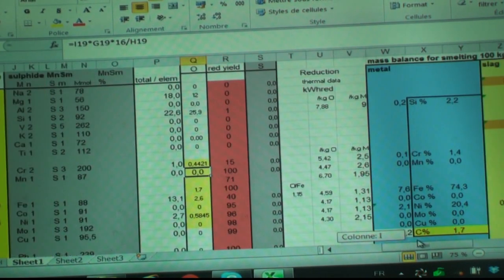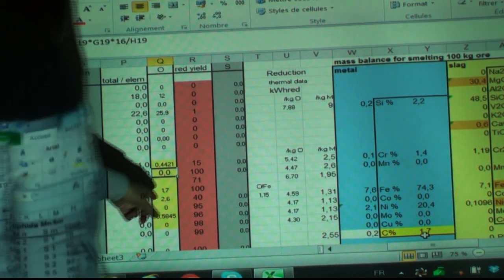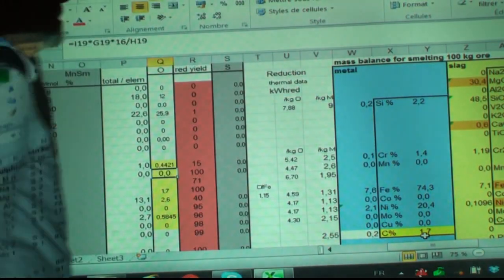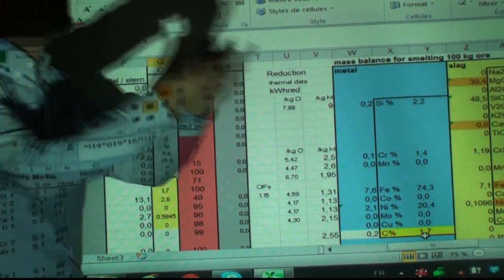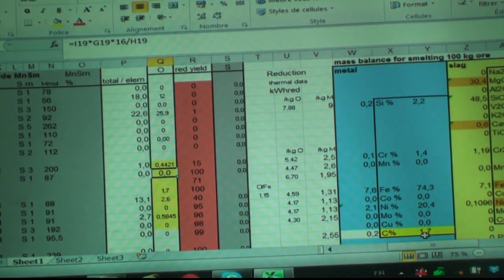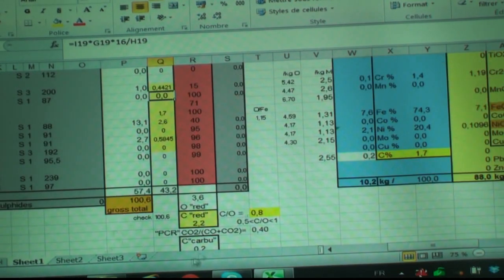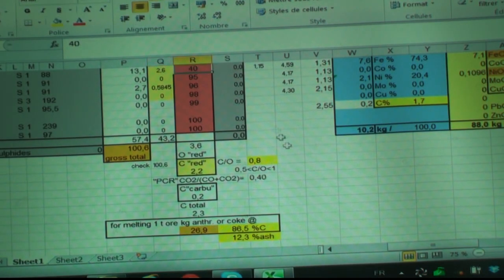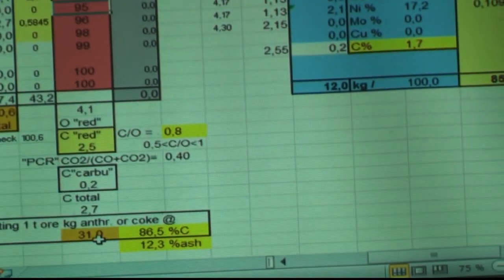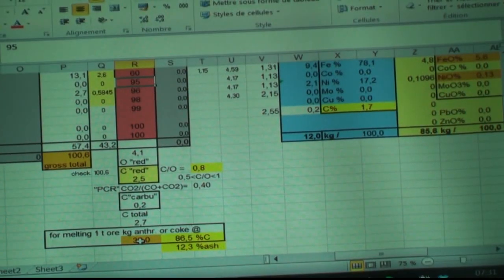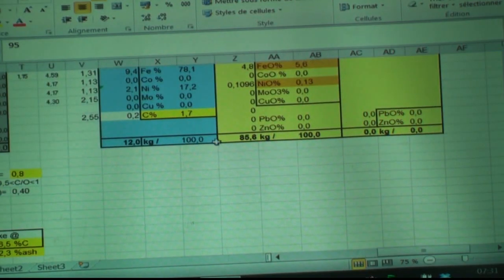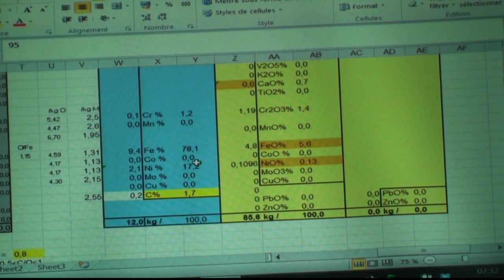The result is in nickel. If I put 40, we have 20% nickel. If I put 60, we will have less, because if you increase the iron, you dilute the nickel. We adjust the reduction yield and we match the nickel. In practice, the operators do not adjust the yield, but they adjust the carbon. If I put 60, you increase the carbon. And this is what the operators adjust. If I increase the iron yield, I have more iron and less nickel.